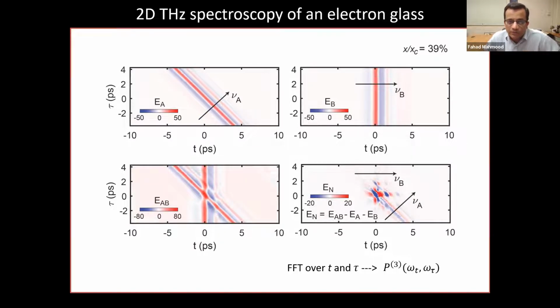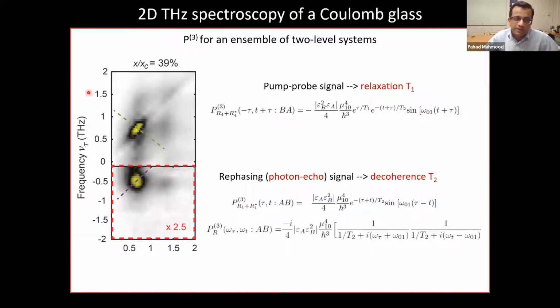Okay, so without going into the time delays, this is the measured experimental signal from one sample of phosphorus doped silicon. What I'm plotting here is the nonlinear polarization as a function of two frequencies, okay? And as you can see in this quadrant here, this is what's known as the rephasing quadrant. You have a very strong response. This is what's known as photon echo in this multidimensional spectroscopy, okay? And it turns out if you work out the math, the width of this echo gives you a measure of the 1/T2 rate for this system, okay? And then you can do that at different frequencies to extract 1/T2 as a function of frequency.